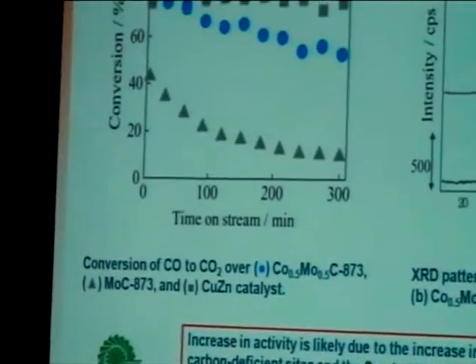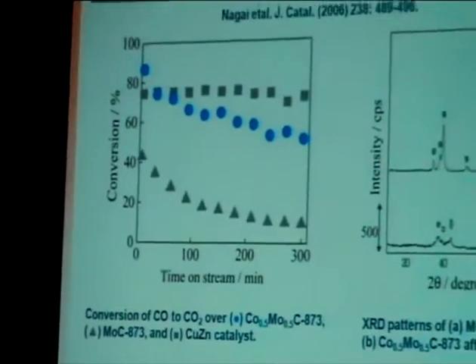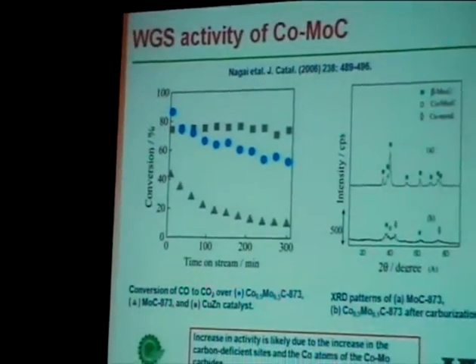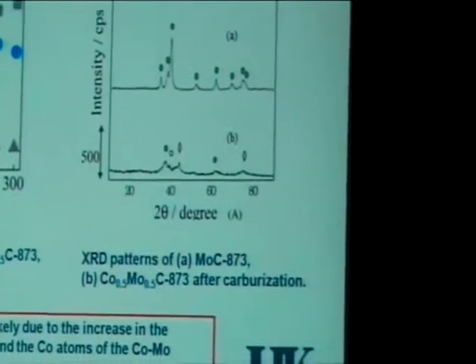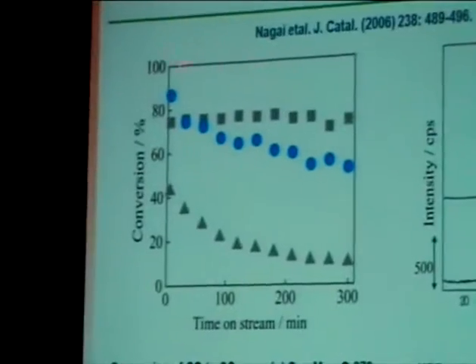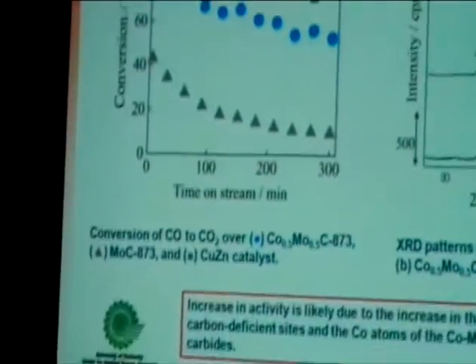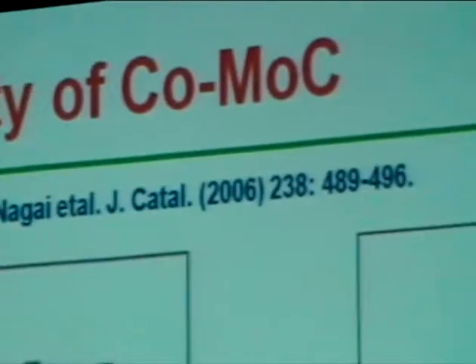Co-workers. What they did was they actually put the cobalt into molybdenum, like 50-50%, and they tested the activity and the conversion. As you see, the conversion looks comparatively stable compared to the pure molybdenum carbide, and it is comparable with the commercial copper zinc catalyst.